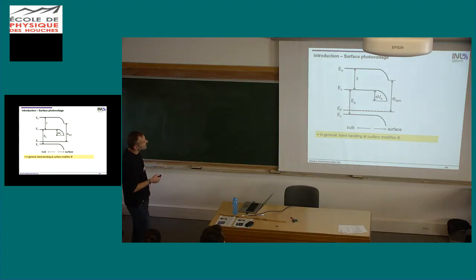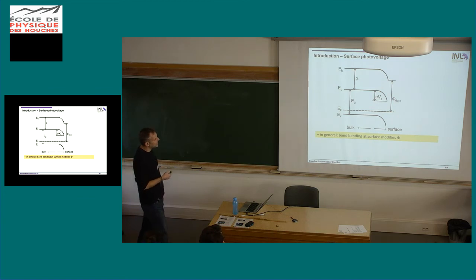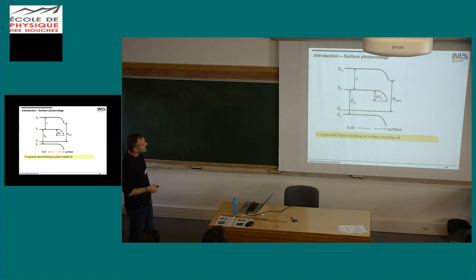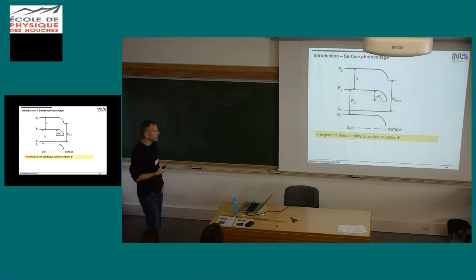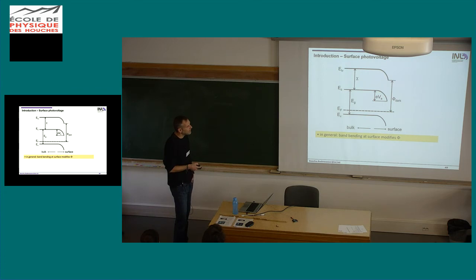So if you have a semiconductor, and also yesterday we saw this in the interpretation of the XPS method. So again, here we have the conduction band, the valence band, the Fermi-Level, and the local vacuum level. So normally your surface is not a perfect surface. You have some defects at your surface, and normally these defects lead to a band bending at the surface because you get charges. And this band bending is then also reflected in the local vacuum level. So what you measure here is the distance from the Fermi-level to the local vacuum level at the surface, obviously.